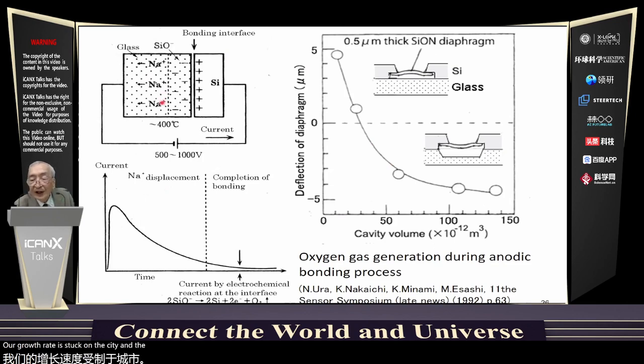and negative high voltage is applied to the glass at 400 degrees centigrade. Positive sodium ions move and the negative space charge layer with SiO minus is formed at the interface with silicon. The glass is electrostatically bonded to the silicon surface. A current is caused by the displacement of the sodium ions. However, we can see a small current even after bonding.